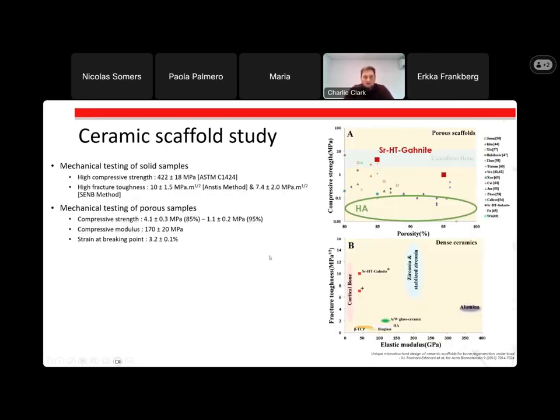So to begin with, they did some mechanical testing of the solid samples. So you can see the compressive strength and the fracture toughness. And they also did some mechanical testing of the porous samples.